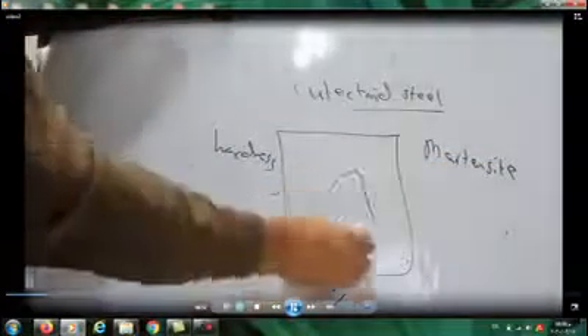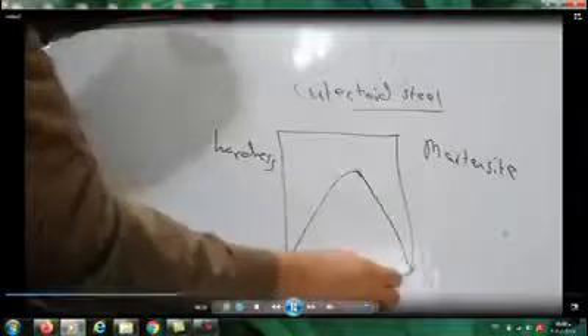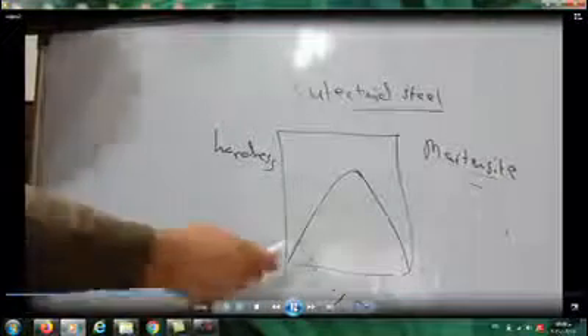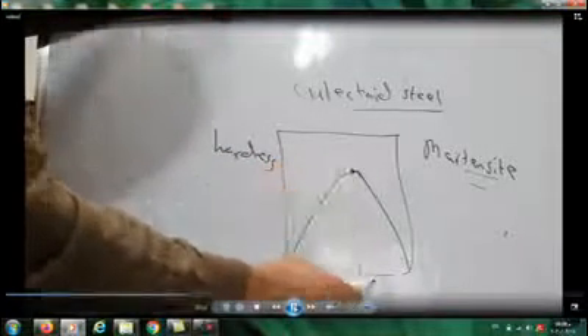If we draw the relationship between the hardness and percent carbon for martensite, we found it something like this. As the carbon content increases in the martensite, the hardness increases up to a maximum value at almost 0.5% carbon. After the 0.5% carbon, the hardness decreases again.